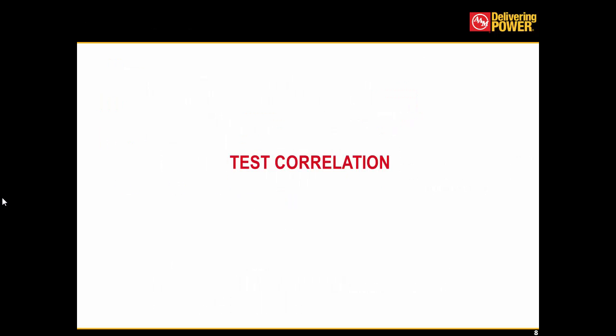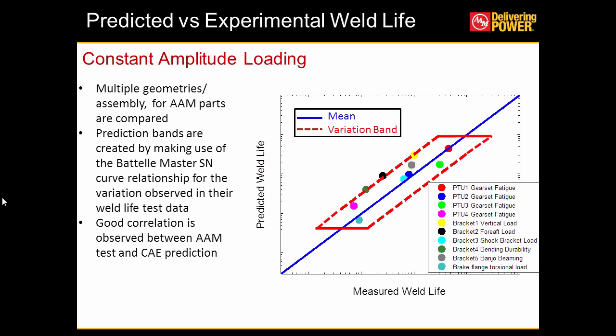So now let's look into the test cases we ran and how we did the correlation. Our first case is a constant amplitude loading scenario. On the x-axis we have the measured weld life, and on the y-axis the predicted weld life. We have more than 10 cases here. The blue line represents the mean, and the dotted red line denotes the variation band. For these cases, which are very different in nature, we observe very good correlation with the test within the variation band. So let's look into the detail of these cases.